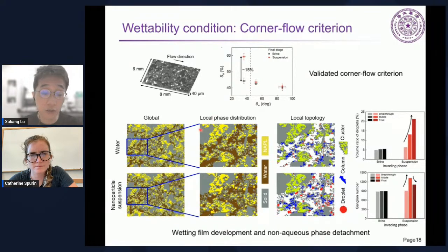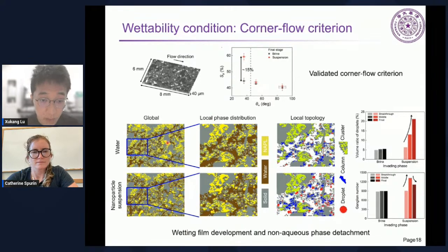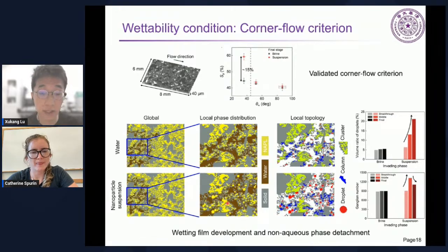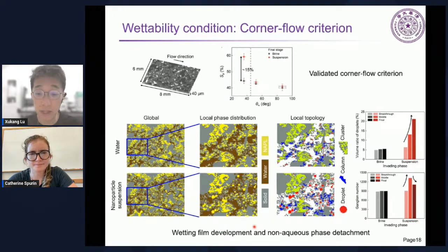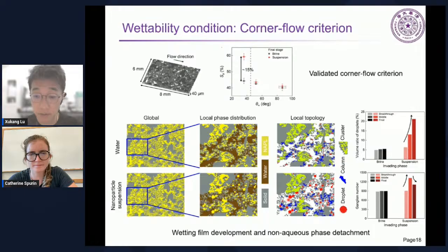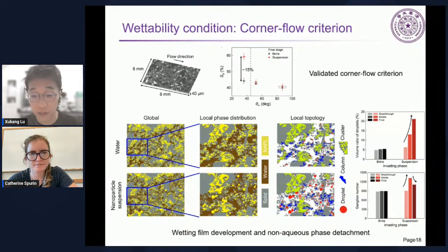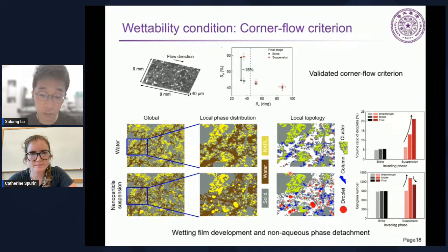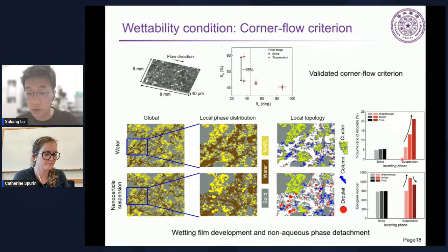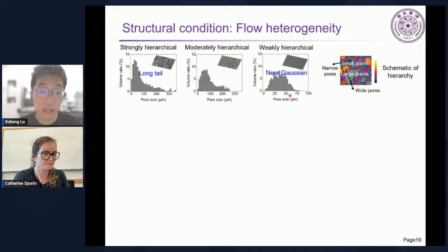And when nanoparticles can play their roles, as shown by the animations here, you can see strong wetting film development, non-aqueous phase detachment, and all this ganglion mobilization. The qualitative observations are consistent with our quantitative statistics of the topology evolution. So the next step is to investigate the structure properties, as we mentioned in the introduction.